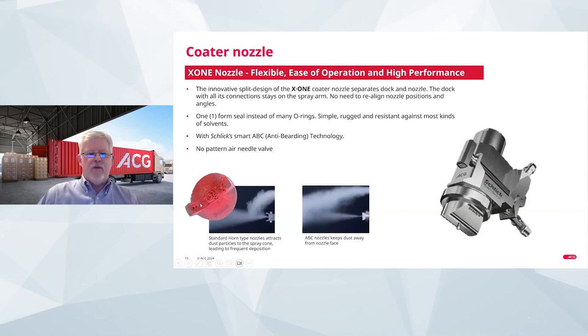Now, what's unique about this is if you look at older type nozzles with horn type pattern air configurations, this type of configuration creates a backflow of air. And you can see in this illustration or photo that the spray formed with this type of nozzle, with a smoke generator, the smoke is actually being drawn into the nozzle because of air eddies that are created. Now, what this does to your spray is this creates a lot of bearding or back spray onto the nozzle, thereby reducing the effectiveness of the nozzle. And if you build up enough of this, you're also going to start to affect the spray pattern itself.